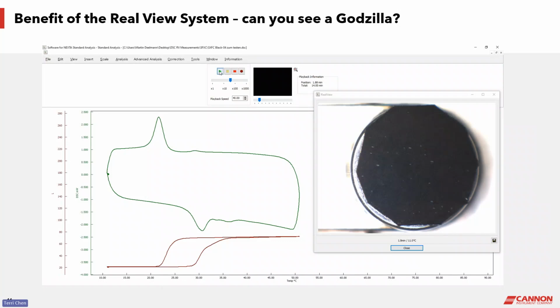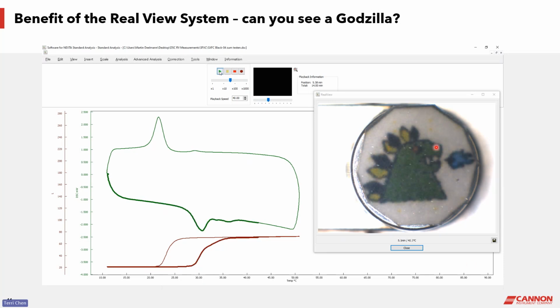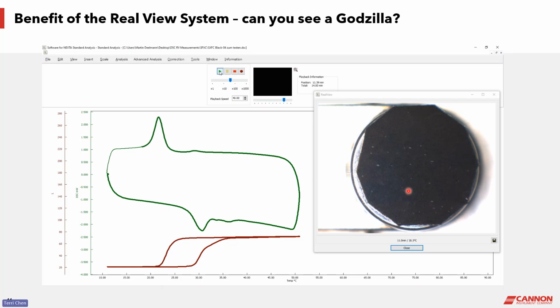Here is a fun application example showing the usefulness of this real-view system. We put a picture underneath a piece of polymer sample. Because the polymer is partially crystallized, it looks black underneath the polarized microscope. However, as we conduct a heating test on this sample, let me play the video here. When the temperature passes its crystal melting temperature, the polymer turns clear. Now we can see through. Now we see the picture underneath the polymer is a picture of Godzilla. Then, as we cool the sample down, the polymer recrystallizes and turns black again.